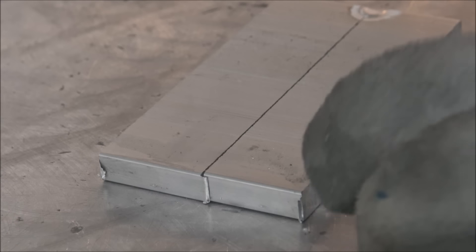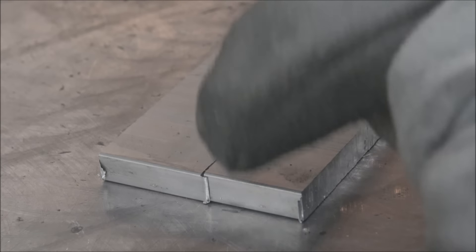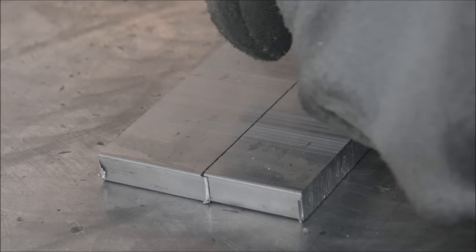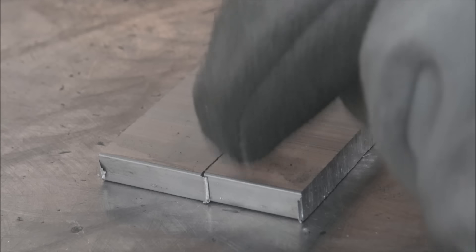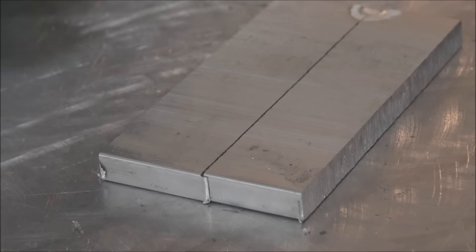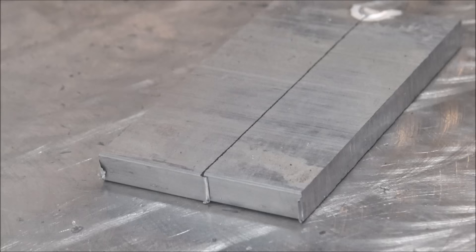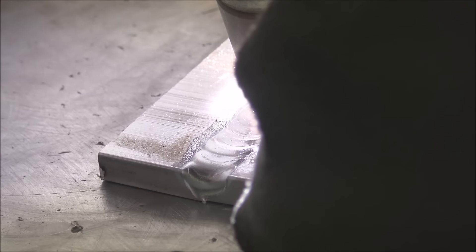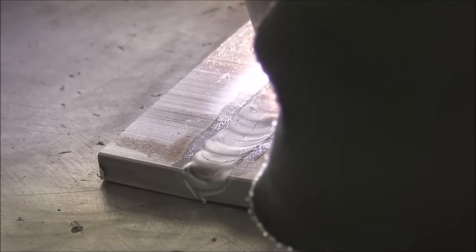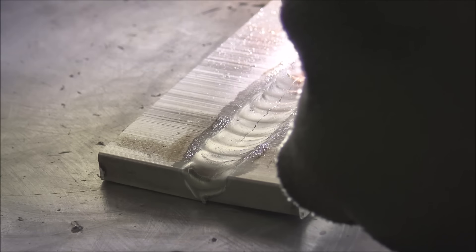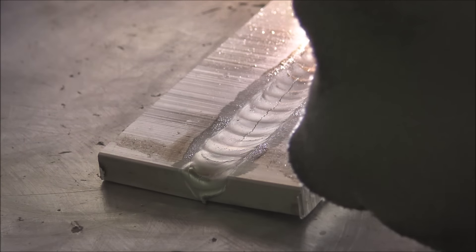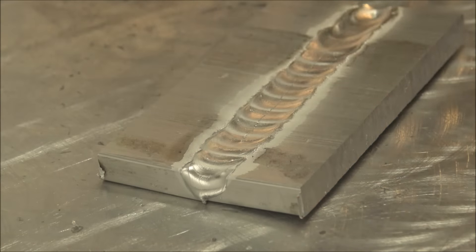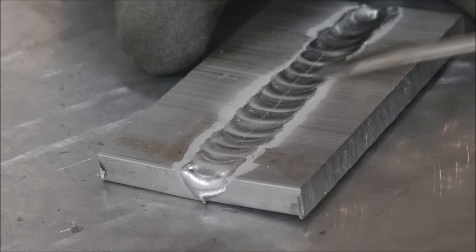Especially with thicker metal because it's got such high thermal conductivity where your little hot weld puddle is, the rest of the metal wants to pull that away and cool it real quick. And that's also why you want to preheat thicker parts when you're welding them. See that crack running down it?